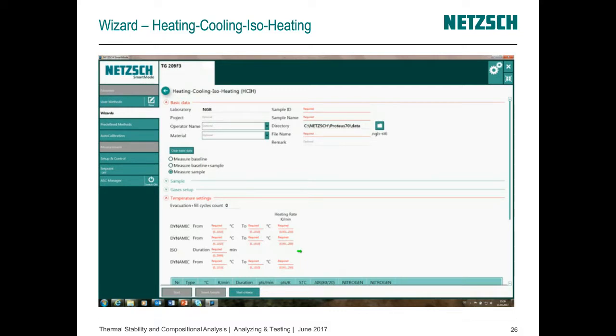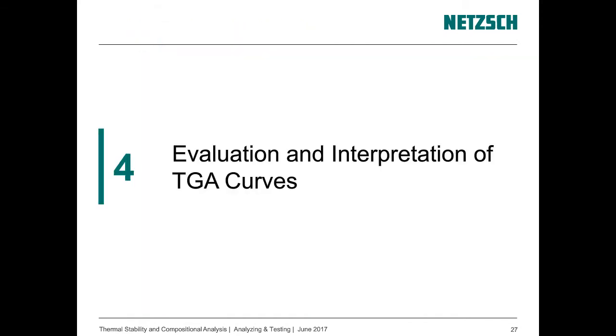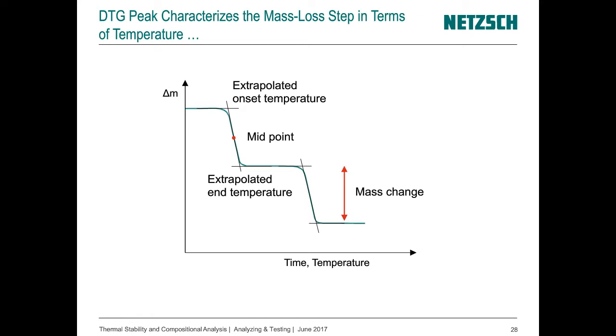Let's go over to the evaluation and the interpretation of TGA curves. And the first thing what I would like to present you is an ideal curve where we can see two steps. And the mass change, of course, is evaluated from the step height. And there are several interesting temperatures for characterizing the mass step, the mass loss step, the extrapolated onset temperature. We have seen it already. A similar temperature we can also evaluate at the end of the step as extrapolated end temperature, and the midpoint, what is in this case the inflection point of the step.